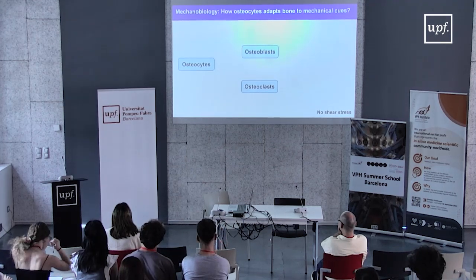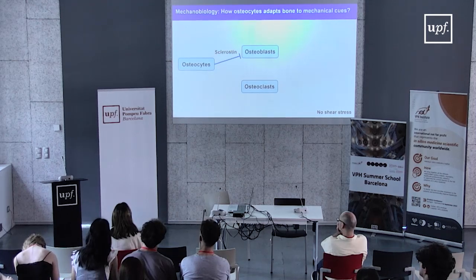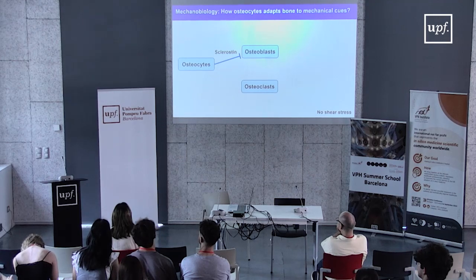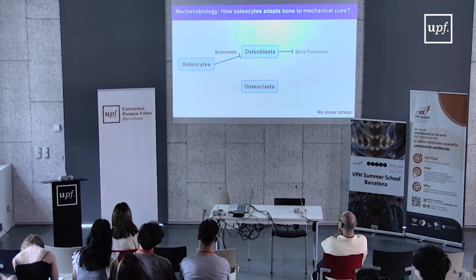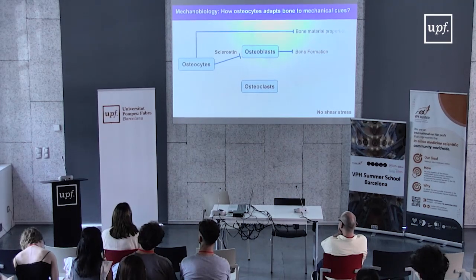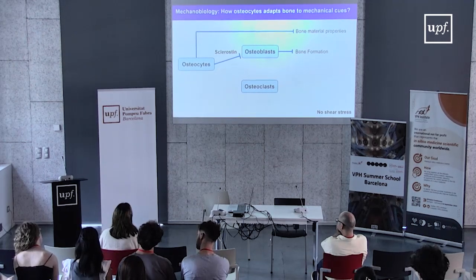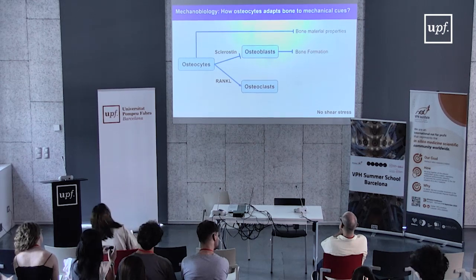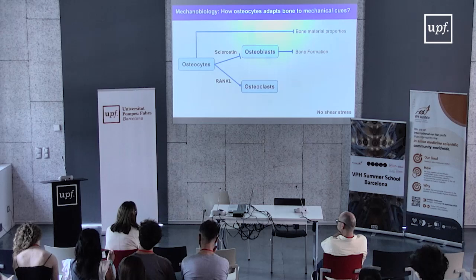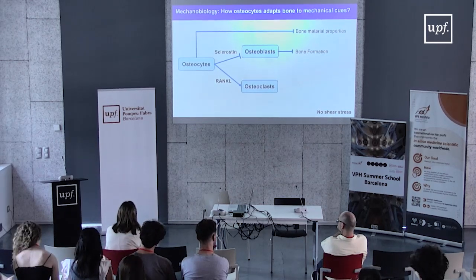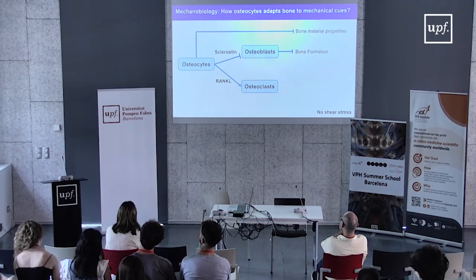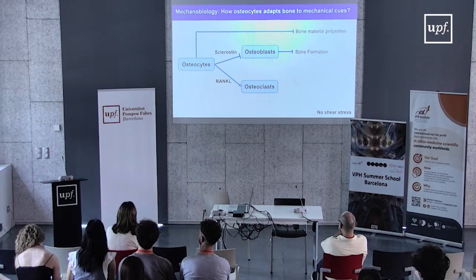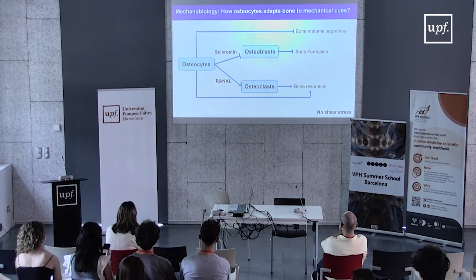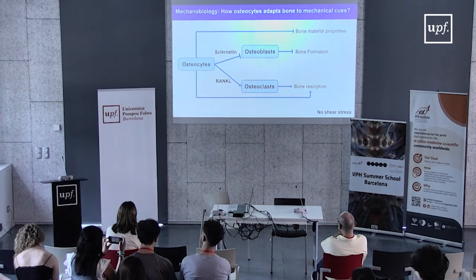In a situation where there are no mechanical forces, osteocytes will secrete other mediators like sclerostin, and sclerostin is an inhibitor of osteoblasts. So when sclerostin is secreted, osteoblasts can no longer carry out bone formation. Osteocytes will also reduce the amount of modification of the material properties, and they will stimulate resorption by osteoclasts through the secretion of RANK ligand. Like that, osteoclasts will remove a small quantum of bone, and hence osteocytes can sense mechanical forces again. So it's really a dynamic process to find the good balance between enough mechanical forces and not enough mechanical forces sensed by osteocytes. And of course, osteocytes can by themselves also induce bone resorption around their dendrites and cell body. And you have really this dynamic cycle which is put in place to adapt to mechanical cues.